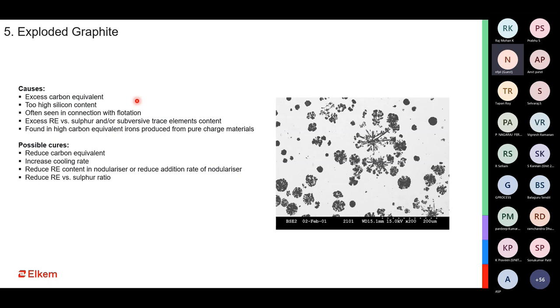So what does this tell us? This tells us that as we go heavy on the sections of the casting, we should try to reduce the rare earth coming into our system. When I'm producing a heavy section, I would try and go for a lower rare earth containing ferrosilicon magnesium. As I'm going towards thin section castings, I can increase the rare earth, because high rare earth and heavy section is not a good combination. So we have to always try to go for a lower rare earth.